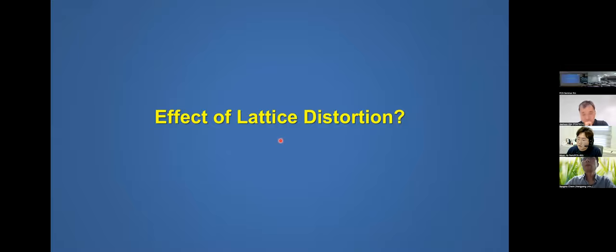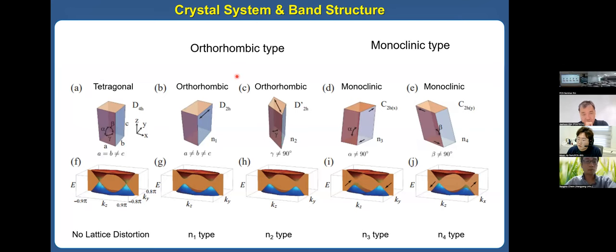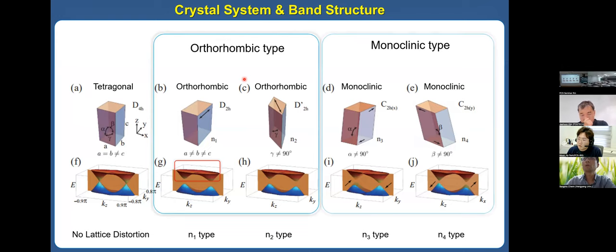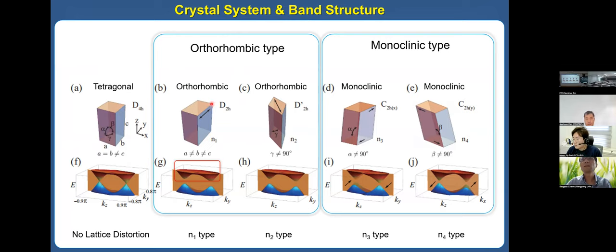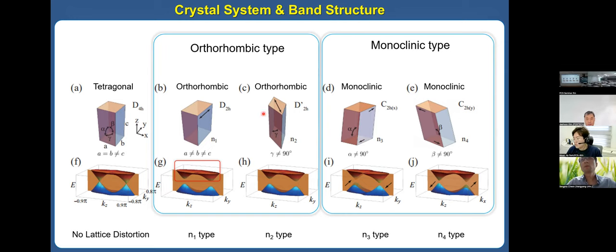What is the effect of lattice distortion? From the tetragonal mother crystal system, if we apply N1 or N2 type lattice distortion, the system is elongated along one axis, giving an orthorhombic crystal system. For N3 and N4 systems, one plane is inclined, giving a monoclinic system. This is consistent with experiment. Also, the Dirac bands are gapped out under lattice distortion.